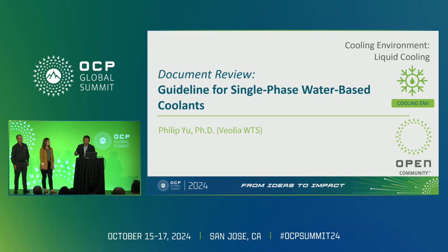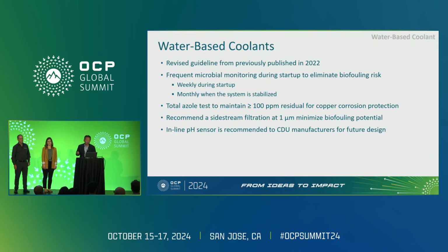So my topic is based on water-based coolant. This revision from the previous document will cover the guideline, safety, how you choose the coolant, the considerations of the coolant, the properties and material compatibility, and what you need to pay attention to when you start it up. Startup is the most important. There are a lot of issues, because when they ship the equipment to the location, it could be pre-tested with some coolant left in there. If they leave it without any care, after 6 months there will be bacteria growing inside the liquid. That's the biggest headache when they try to start it up.